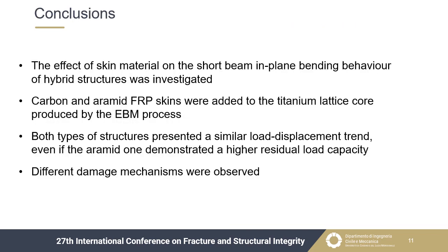A study about the in-plane flexural behavior of different FRP titanium structures is presented in this work. In particular, 2 different types of FRP skins were considered, carbon and aramid fibers, while the core, presenting a lattice structure, was made of titanium alloy. The lattice cores were made through EBM, while the skins were added through autoclave vacuum bagging.